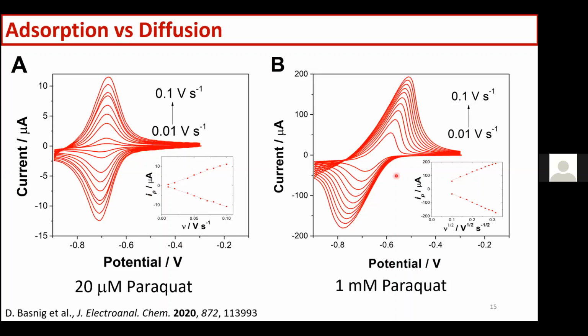When we were increasing the paraquat to 1 millimolar, we started to see a diffusive behavior with a larger peak-to-peak separation, and the peak current was linearly dependent on the square root of the scan rate.